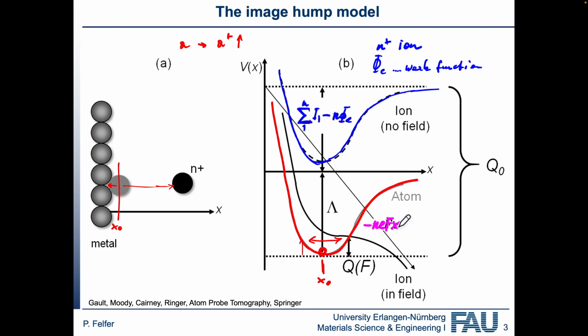And so if this term becomes large enough, and here we've got a couple of electron volts energies typically, so you can imagine we need volts per nanometer kind of fields in order to be able to make a contribution to this. And if we have that, so volts per nanometer level fields, then we will get a potential energy curve that looks like this, which is just a modification of this potential energy curve plus the energy contribution from the field.